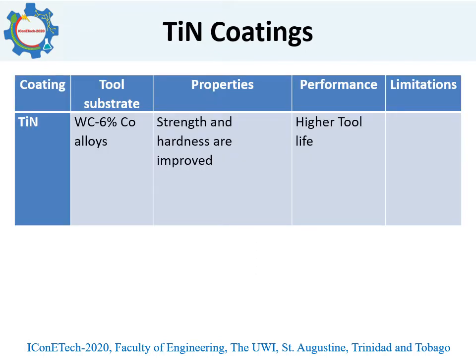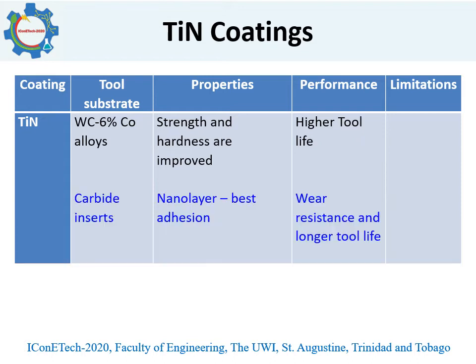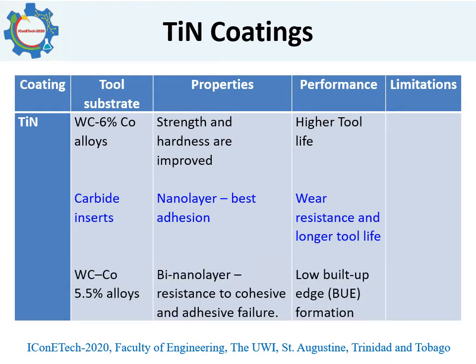Titanium nitride is one of the most common applications. It can be done with both PVD as well as CVD. What has been noticed is that a monolayer can be applied on carbides. For example, as we can see here, the normal carbide with 6% cobalt binder, that is the traditional carbide, has its strength and hardness improved, and consequently they provide higher tool life. You can also provide nano layers with best adhesion and wear resistance and longer life.